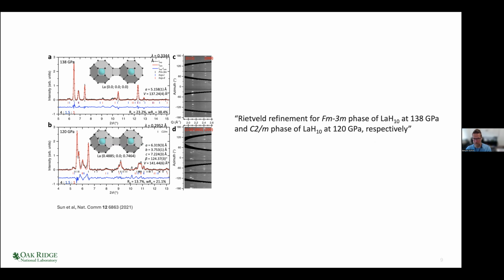So in my opinion, these data have been overanalyzed, and they pulled out quantitative phase percentages, and you can see these very precise R factors. Those are essentially meaningless because the intensity information is not in the data. So I just wanted to say that out loud, because unfortunately you do see a lot of this in high pressure literature.